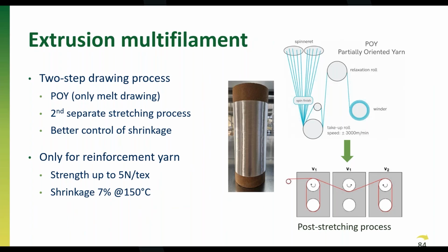And in this case, the take-up roll is much higher in speed. For the one-step drawing process, that was between 300 and 500 meters a minute. In this case, it's around 3,000 meters a minute, so almost tenfold of that speed. And then in the second step, we do a post-stretching process in which we reheat the filaments in